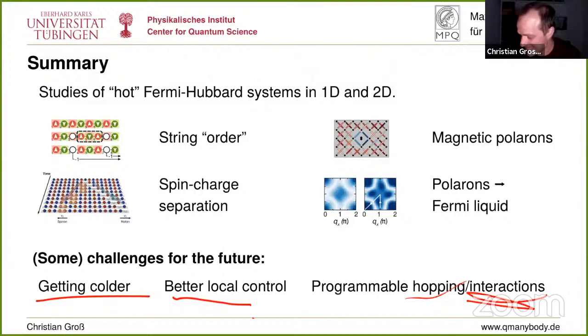The short answer is yes. That's exactly what the team of Jian-Wei Pan has done in their system. So you imbalance them a little bit. That one is basically in the metallic phase. So you have holes, and there's a lot of entropy capacity. And the nice thing with the layer is you have a coupling over a surface instead of over an edge, as if you do that in a single layer, right? So you just have better contact.